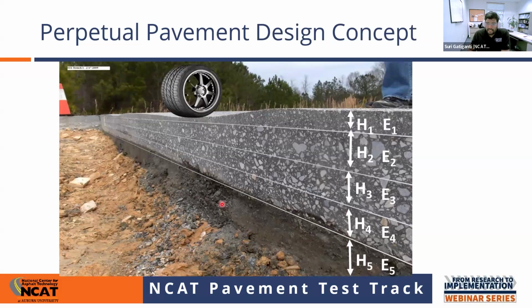As I said, this is a schematic that shows what we will be doing. The perpetual pavement concept itself is controlling the bottom-up fatigue cracking. And we know once we apply a load on top of an asphalt concrete pavement, because it's flexible, it generates tensile stresses at the bottom of the AC. So our goal from the design perspective is to control that strain level to a certain value, so that we are not initiating the bottom-up fatigue cracking. And also to limit the strain on top of the subgrade, basically by controlling the stresses that are going onto the subgrade, so that we are not seeing any structural rutting happening.